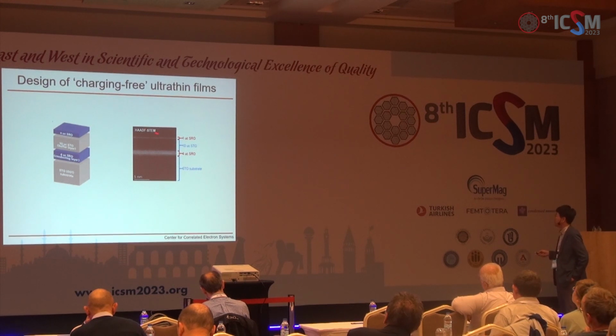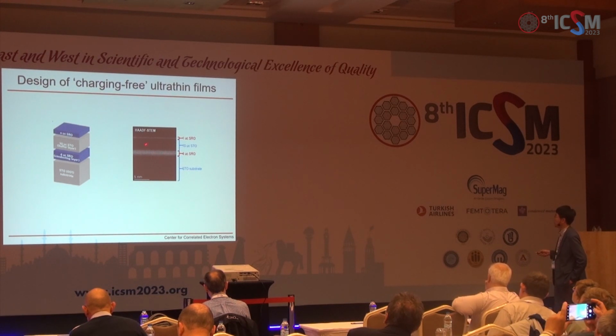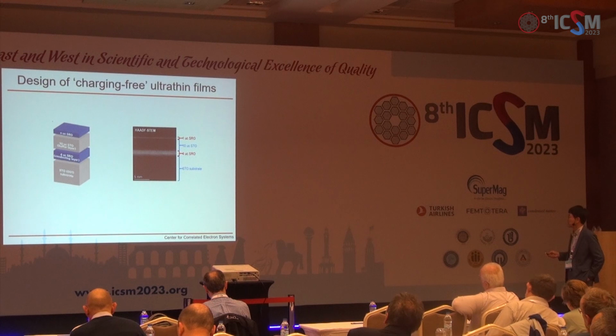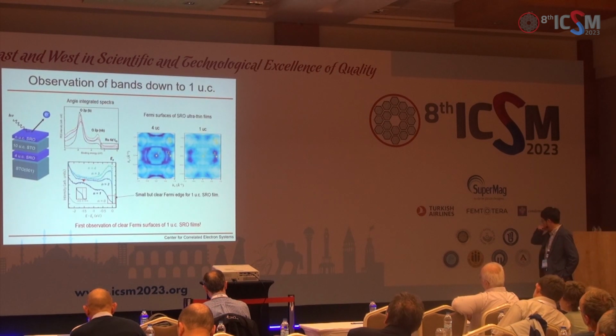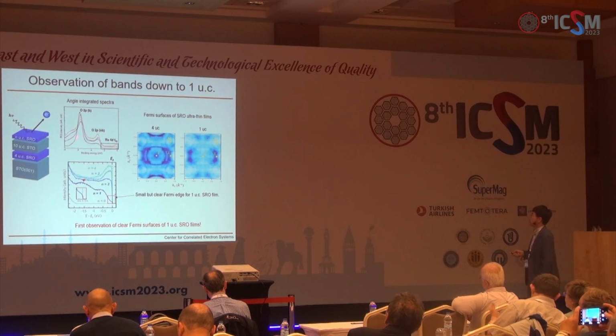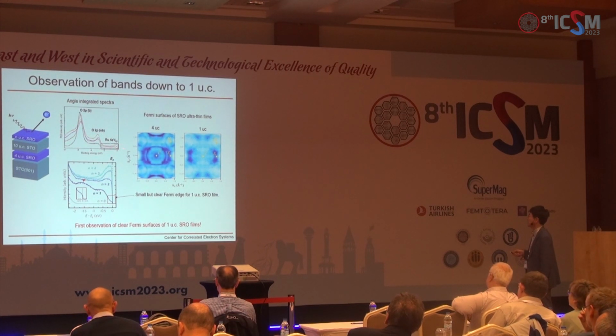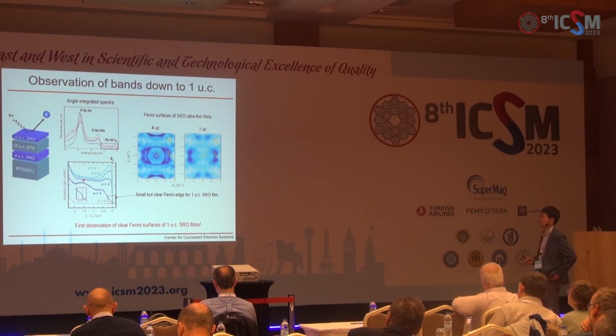Here I show you a TEM picture of this structure. We have STO, 4 unit cells of SRO, 10 unit cells of STO, and 1 unit cell of SRO. So we can grow a fairly nice 1-unit-cell SRO on top of this structure. Now we took ARPES data, photoemission data, as a function of top SRO film thickness. Let's focus on the near-Fermi-level structures. Without the strontium ruthenate layer, I'm looking at 10-unit-cell STO, so it's nothing, because STO is an insulator. I have no spectral weight.